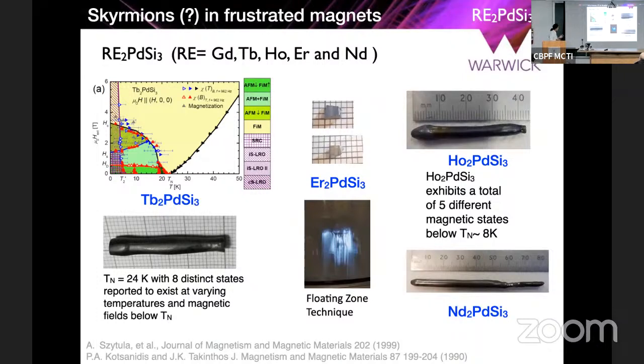And since studying the gadolinium, palladium, silicon crystals, we've been able to produce crystals of the entire family of these rare earths. And these crystals are produced by the floating zone technique, where we've modified our floating zone furnace to be able to produce crystals of these intermetallics. Now, once again, I'd like to emphasize that these are all very old materials. These have been very well studied. In fact, these papers in 1990 and 1999 actually map out most of the magnetic properties of these materials.